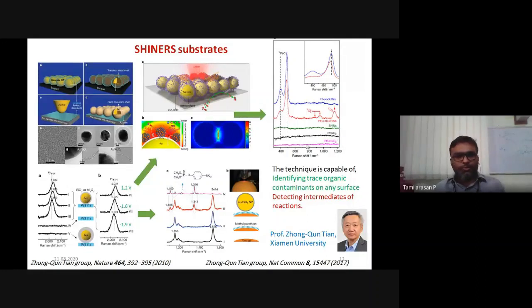If you put only SiO2, there was no peak here. Or it may be people would have claimed it may be because of the presence of Fe. No, it is not, because if you remove Fe, then once again you didn't get any peak here. Or people would have claimed that it is the peak from the particles, the SHINE particles. The SHINE particles also show no peak here. And when you put both the PtFe and SHINE particles, and if you allow carbon monoxide and oxygen, then it gives you a very strong peak here, that is corresponding to Pt-CO formation.